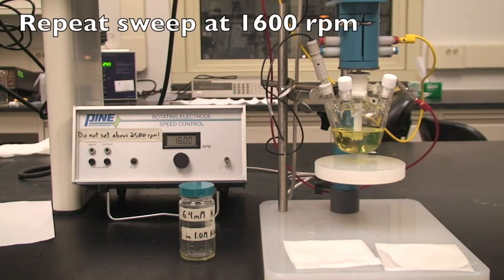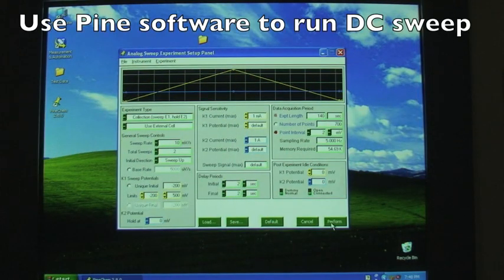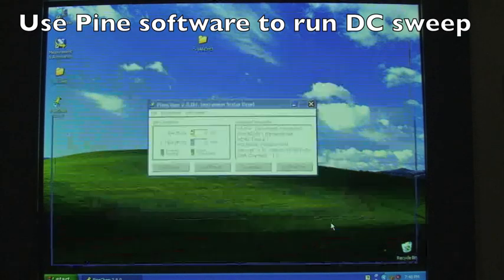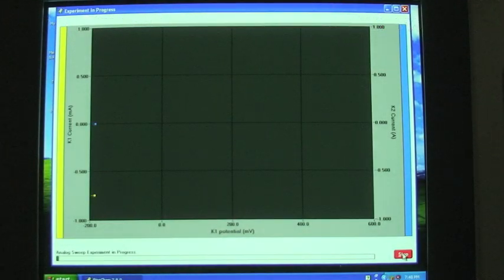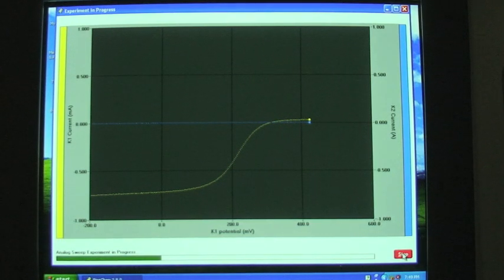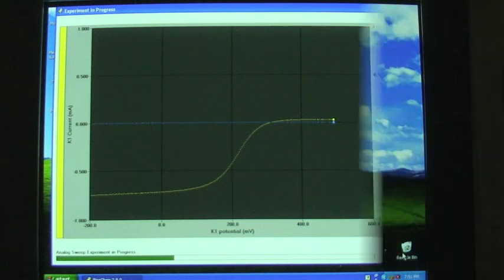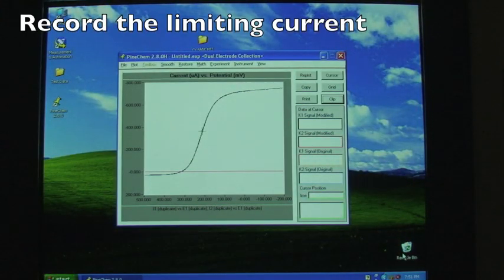We will run a final sweep with a rotation rate of 1600 RPM. The DC sweep is performed identical to the two previous ones. The limiting current observed here should be larger than that observed at either 400 or 900 RPM. The Levich equation can be used to relate the observed current density as a function of the rotation rate. If the electrode area, solution viscosity, and concentration of the active species are known, then the equation can be used to calculate the diffusion coefficient of the active species. Conversely, if the diffusion constant is already known, then the concentration of the solution can be determined. Make sure to record the final limiting current value.